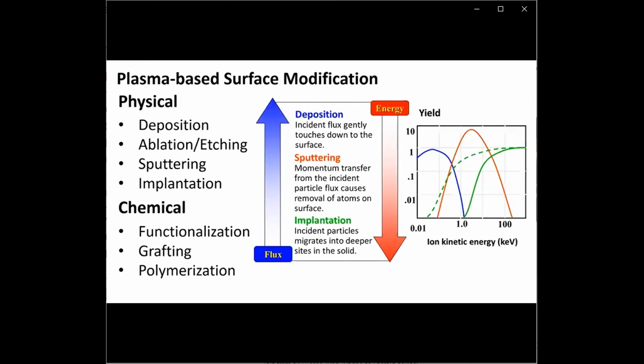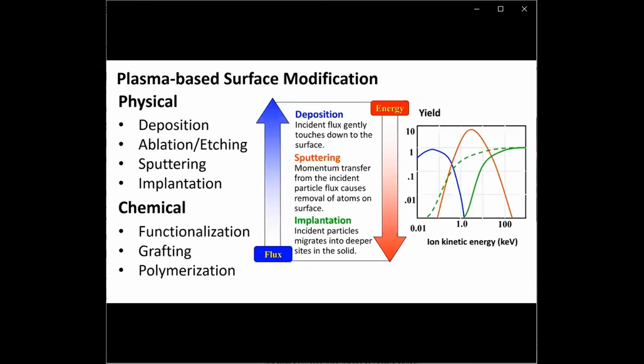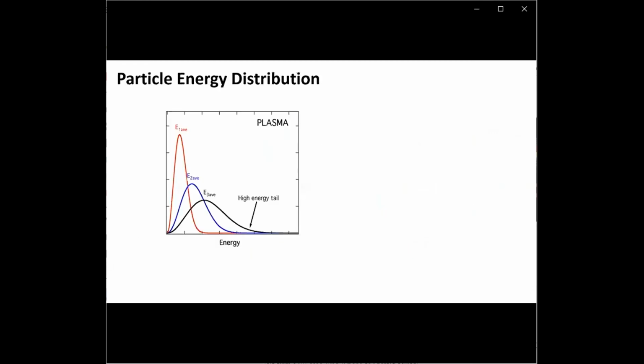On the other hand, a chemical process induces chemical changes on the surface. For instance, if you are attaching functional groups on the surface, this is a functionalization process. If you want a more permanent effect on the surface, then you can graft the surface. And finally, you can also grow a thin layer of polymer on the surface, which is actually similar to a deposition process. In addition, you can actually control the particle energy distribution of your gas discharge, such as this one.